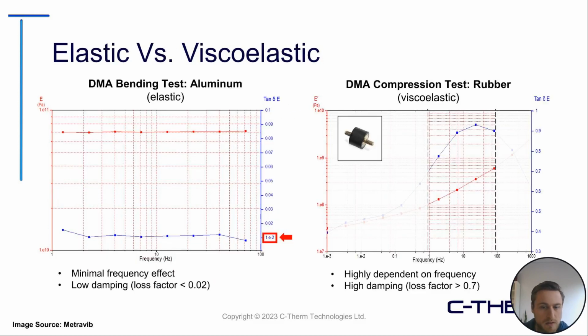And just as a fun comparison between elastic and viscoelastic materials, on the left is a frequency sweep on a piece of aluminum, which was being bent using a DMA test. We consider aluminum to be elastic, and these material properties kind of support that. The modulus is consistent from about 1.5 hertz up to 70 hertz, with a minimal frequency effect.